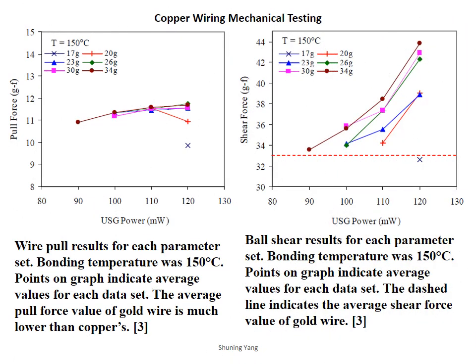On the next page, the left image indicates wire pull results for each parameter set. Bonding temperature was 150 degrees centigrade. Points on the graph indicate average values for each data set. The average pull force value of gold wire is much lower than copper's.